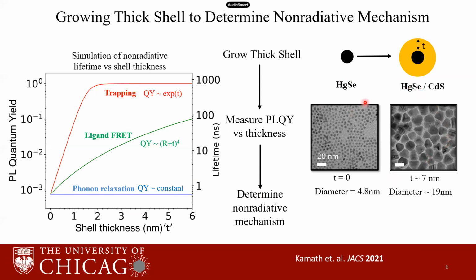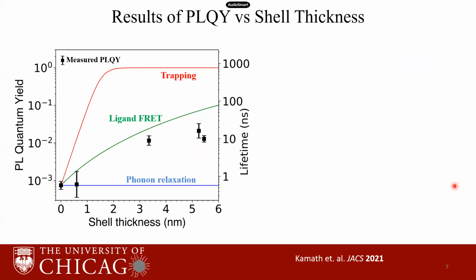We have used mercury selenide as the model system for mid-infrared transitions, and I have grown a thick cadmium sulfide shell around these mercury selenide core quantum dots. As we can see from these electron microscopy images, we are able to grow thick shells roughly uniformly up to thicknesses of 7 nanometers. So now that we have a method to grow a shell around the quantum dot, we need to look at the quantum yield as a function of thickness to determine the mechanism.